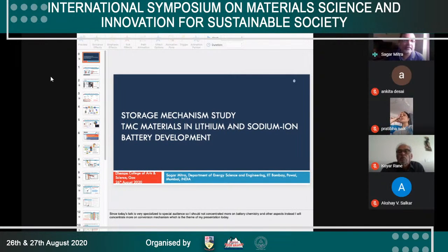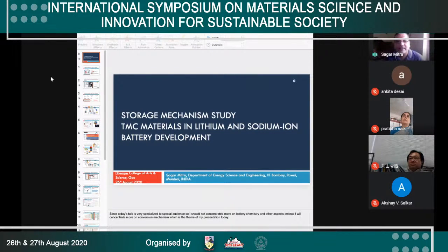If you look at the lithium-ion battery at a glance, at the atomic level, one side is lithium cobalt oxide, which is well known as the cathode. The other side is graphite, which is known as the anode. When you make a battery, you need to charge it to create a potential difference between these two, so that ions can move faster. In the charging process, the graphite is not lithiated, so the lithium comes out from the lithium cobalt oxide structure and goes to the graphite.